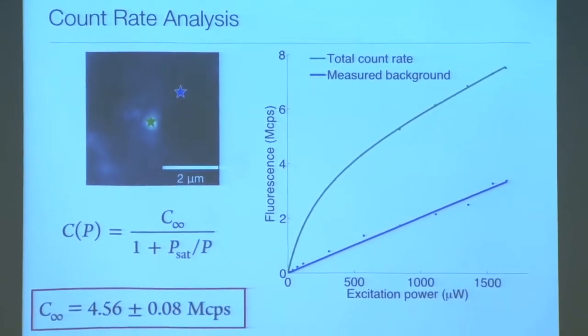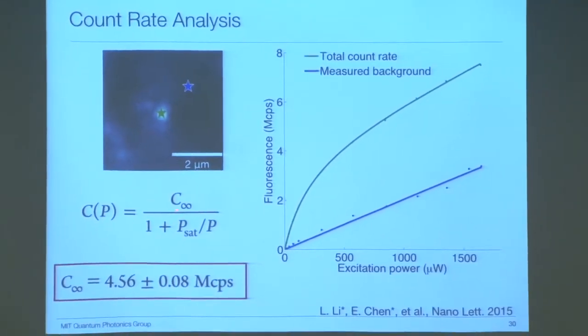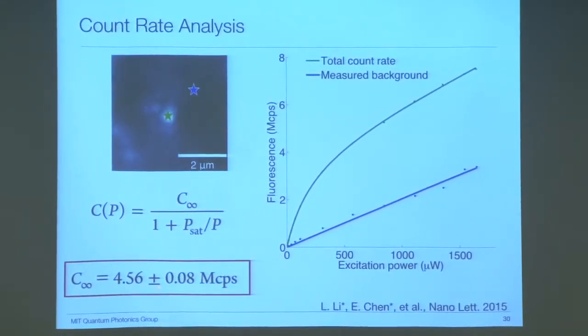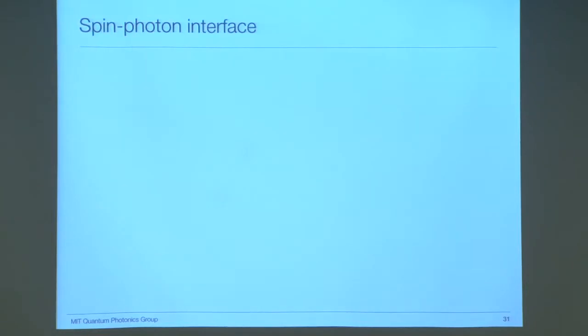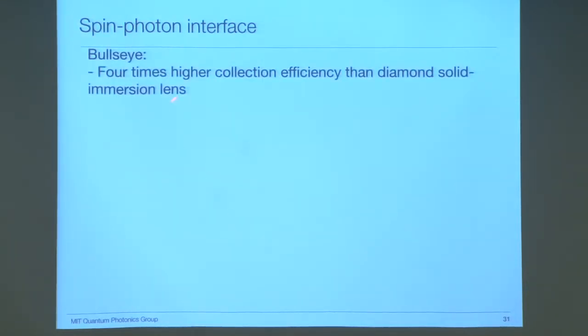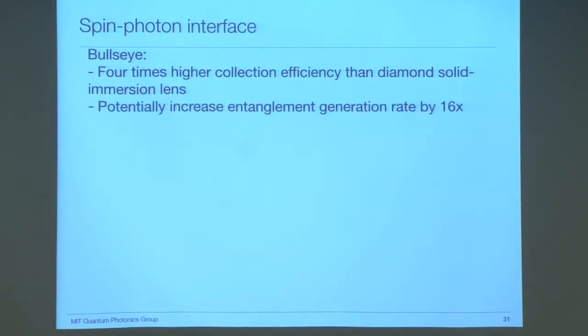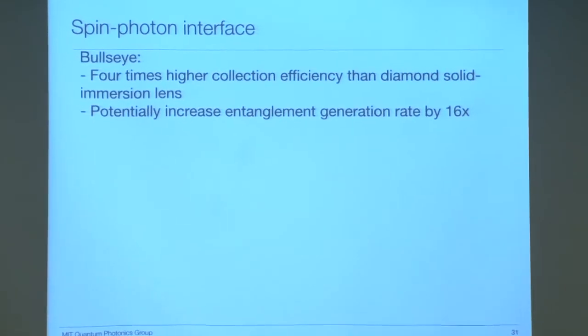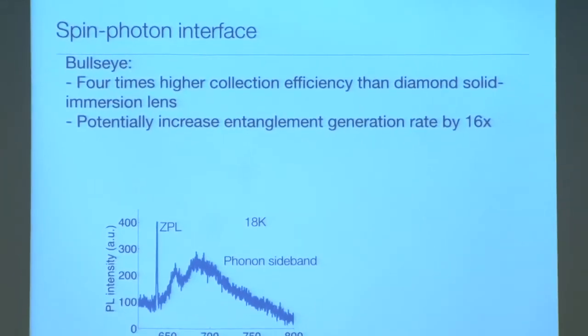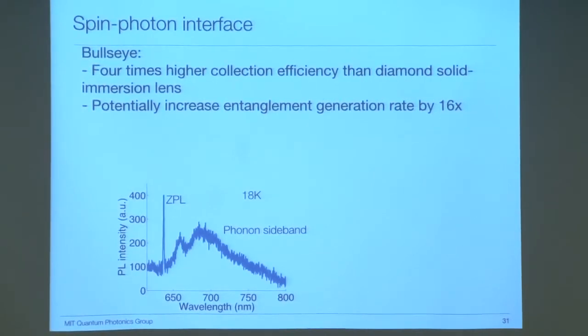The estimated saturated count rate is about 4.5 megacounts per second at a saturation power of about 80 microwatts. And this is a record high count rate collected from a single NV. It represents 4 times higher collection efficiency than the diamond solid immersion lens, and has the potential to increase the entanglement generation rate by 16 times. But 16 times is not good enough.